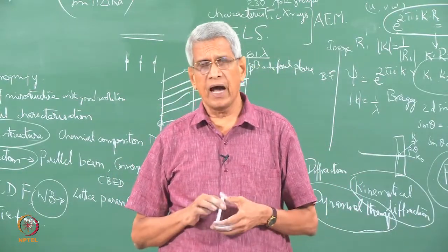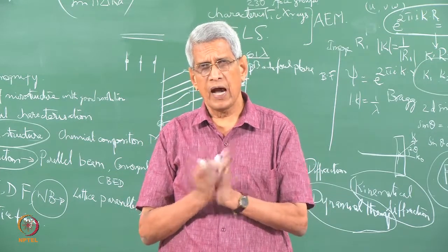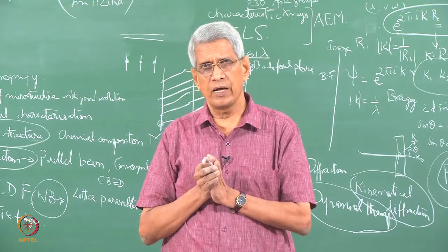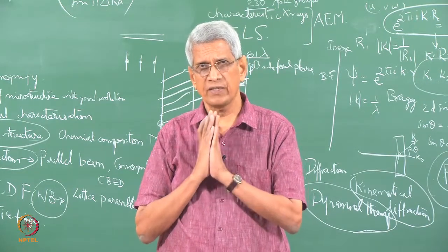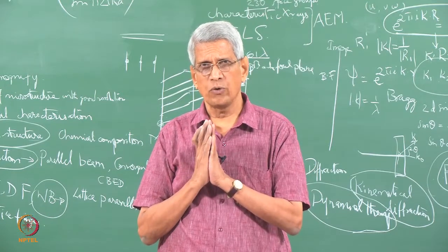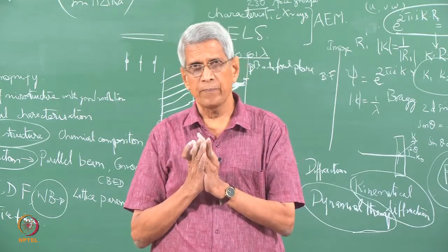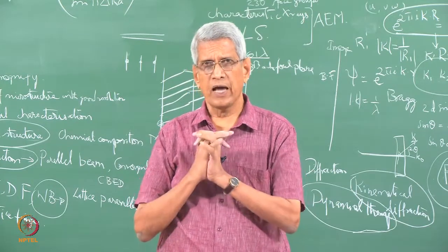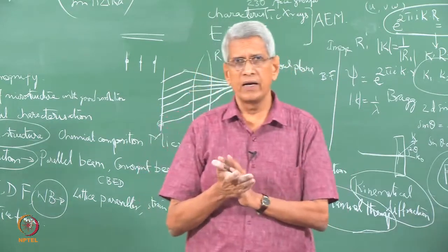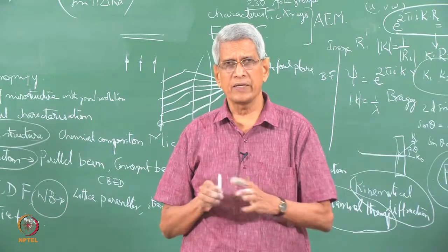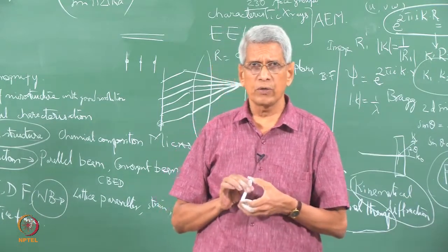The other case is that if we choose many diffracted beams and allow all of them to interfere again, that will give rise to a lattice fringe contrast, which is called phase contrast in microscopy, and that could be used to get information about the atomic distribution, or atomic resolution microscopy. These are all the various methods and classifications I had given on how to go about it.